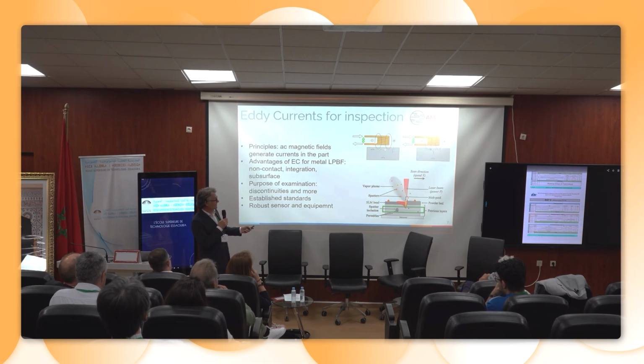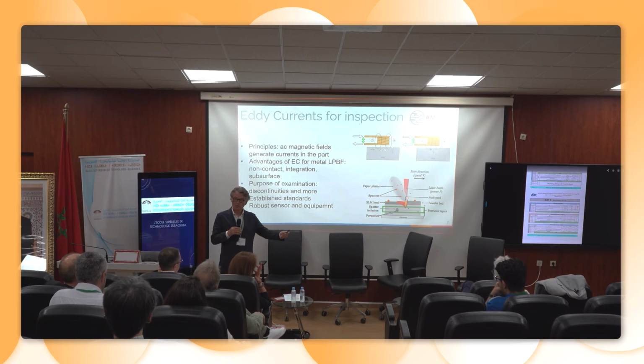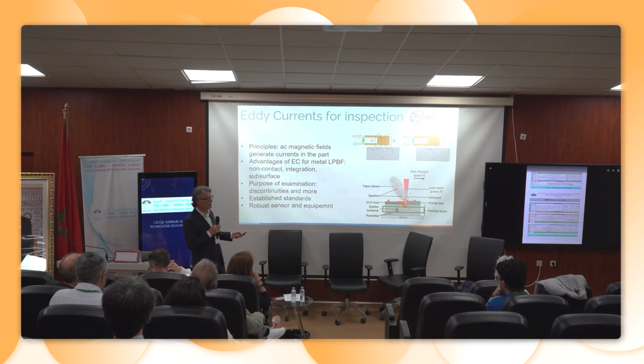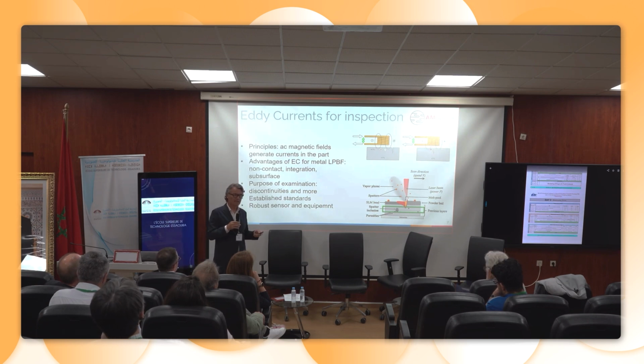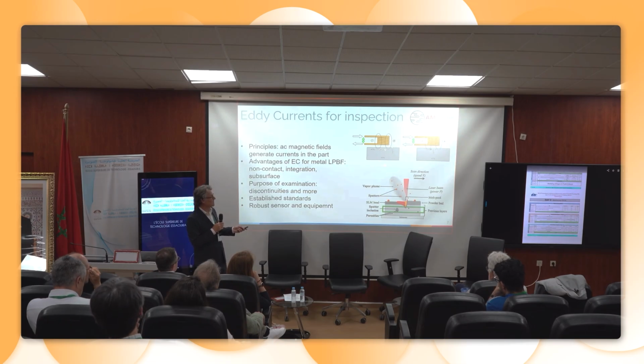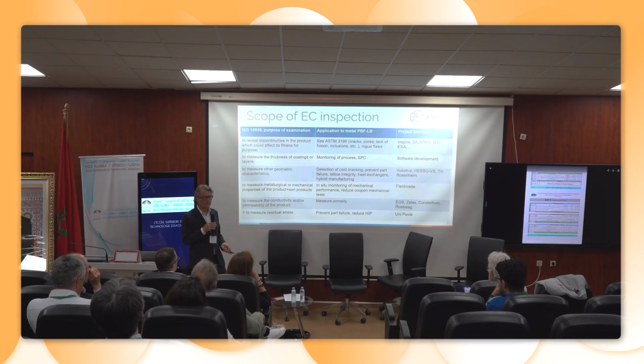So the idea is that the sensor is a coil. The sensor travels with the recoater, which is spreading a fresh powder bed. And the sensor can measure the consolidated part of the build plate, which is the metal part that has been melted and resolidified. And it measures that in, let's say, the cold state, so after the melting has been done. And the system is able to detect a variety of features. And the good point is that, again, it's not me telling you what the system can detect. This is already well described in the standard.